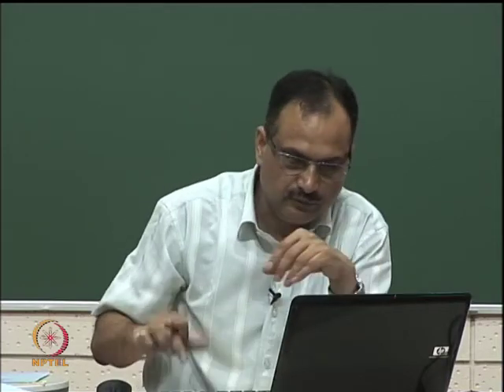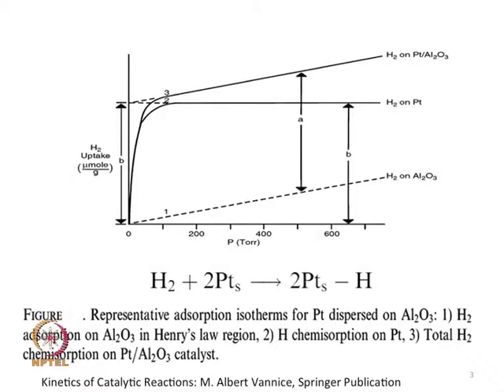You have to ensure there is no chemisorption on the support when you have a bimetallic catalyst or metal on support. For a bimetallic system like rhodium-molybdenum, you sometimes get a total number of sites. To get individual dispersion for a given component, prepare two batches — rhodium on alumina and molybdenum on alumina separately — then take the rhodium-molybdenum on alumina and compare the chemisorption graphs to check whether there is chemisorption of hydrogen on alumina or not. Generally, chemisorption of hydrogen on alumina is very weak, following Henry's law: v ∝ kP.